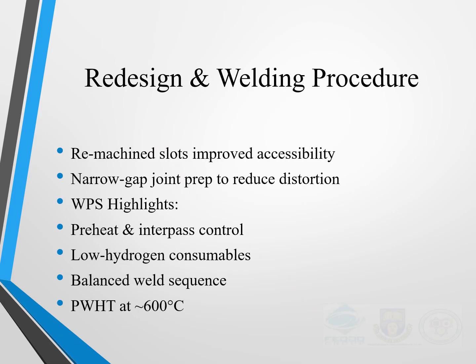For the redesign and WPS, one key intervention was to remachine the slots in the base plate. This gave welders better access and also helped reduce distortion. We recommended a narrow gap joint preparation. This minimizes weld volume and heat input compared to a conventional V-groove. The WPS specified preheating, low hydrogen electrodes, a balanced welding sequence to control distortion, and post-weld heat treatment at around 600 degrees.